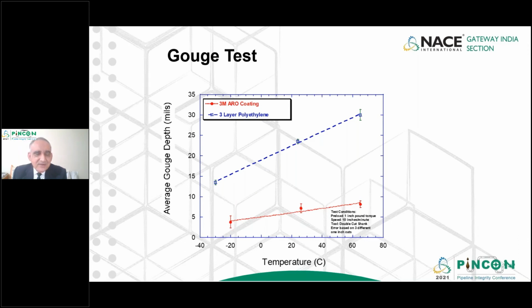So just look at this data. If we do the gouge test at minus 20 degrees Celsius, there is some difference because polyethylene actually gets cut with the gouging action, and the ARO coating does not. Very little impact. But when we do the same test at a temperature like 40 degrees Celsius, there's a deeper cut in the case of three-layer polyethylene coated pipe. That's called a very high gouge depth. We have data that shows that almost the entire thickness of polyethylene, which is about 3000 microns, gets cut at this temperature. While if we do it with ARO, a very minimal inscription is noticed. Very minimal, maybe 10%, 15% depth. In the case of three-layer polyethylene coated, we see like 75, 80% depth.